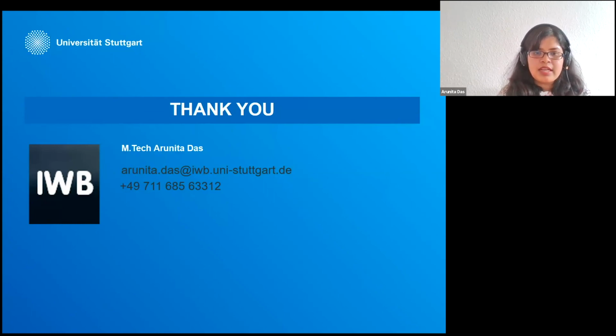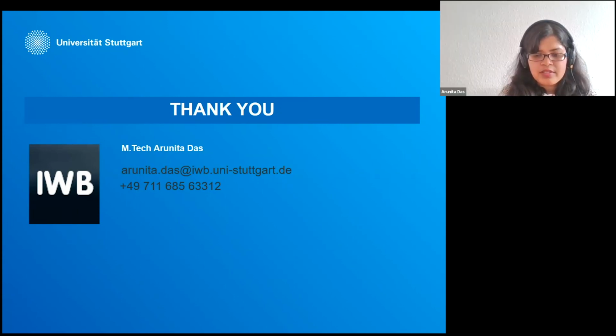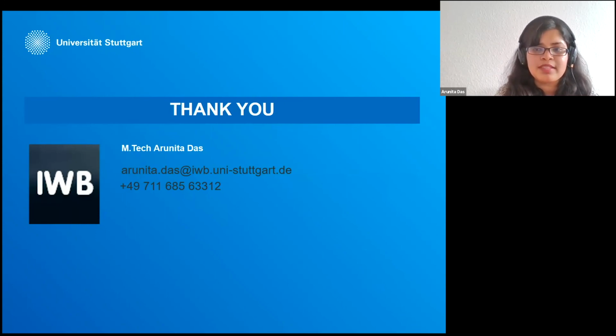Basically there are some studies and literature already. If you are interested, I can share them from our university. There were already some studies on the degradation of concrete in case of fire. Concrete compression strength, tensile strength, everything were pre-calculated, and I considered those values and incorporated them in this software. For my particular study, I didn't consider this part, because these are already calculated. My focus was to check the bond stress scenario after fire, or the residual bond capacity.